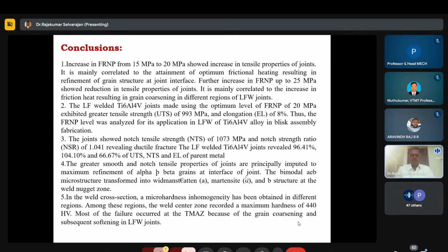So the greater smooth and notch strength of joints are principally attributed to maximum refinement of alpha beta grains at the interface region, and the bimodal microstructure is transformed into the Widmanstätten structure. This is the reason to achieve the maximum tensile strength.